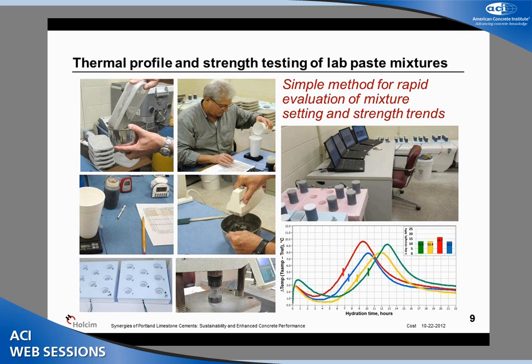Now, these paste mixtures are done primarily because it's a very simple and very rapid way to characterize material performance trends, both with respect to setting and strength. What we do is we actually batch the paste with a kitchen mixer, mix for about 60 seconds, and fill 2x4 cylinder molds with paste. We can do from 3 to 5 dozen of these mixtures in a 3-hour session.